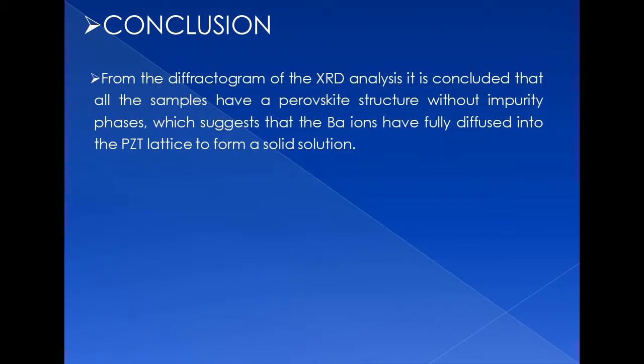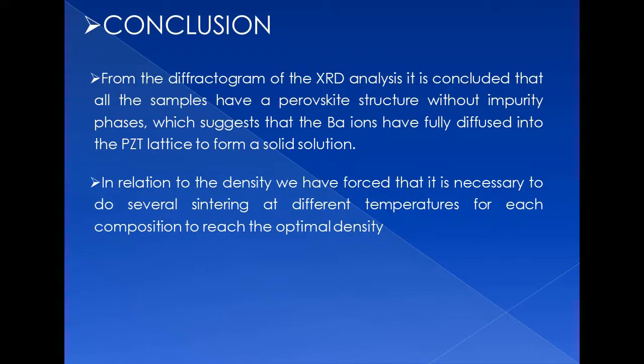Conclusion. From the diffractogram of XRD analysis, it is concluded that all samples have perovskite structures without impurity phases, which suggests that the barium ion has fully diffused into the PZT lattice to form a solid solution. In relation to the density, we have found that it is necessary to do several sinterings at different temperatures for each composition to reach the optimal density.